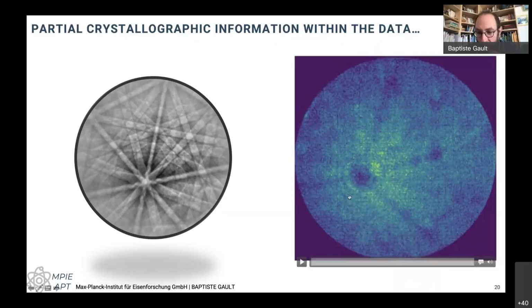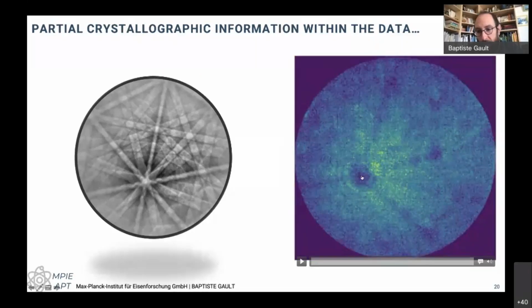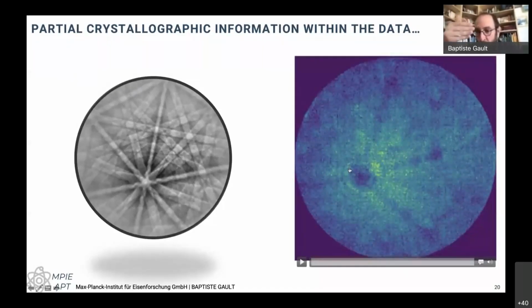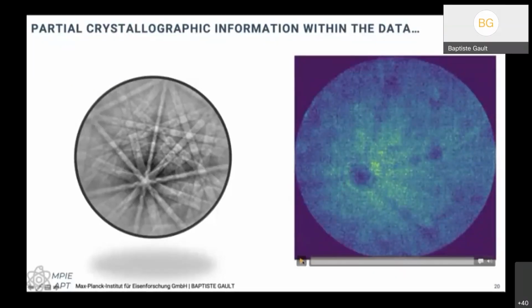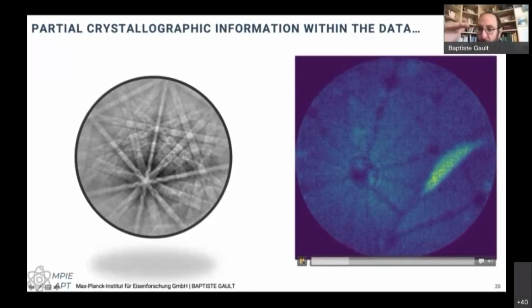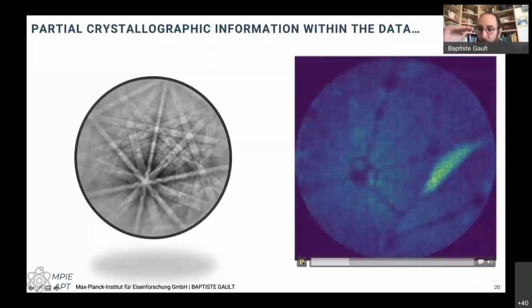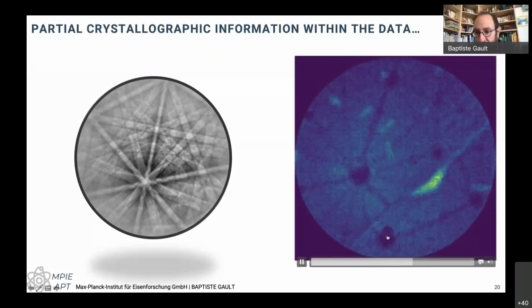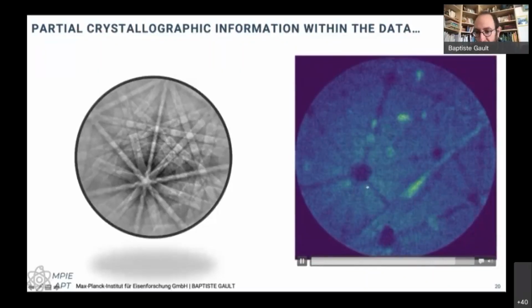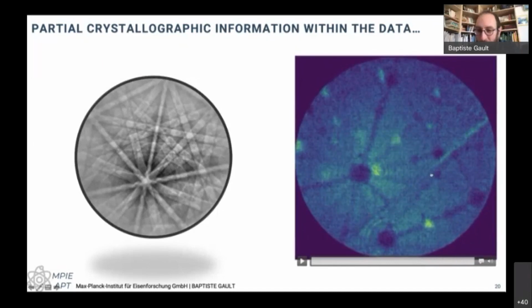But also, let me show you this. Here you see a certain pattern with a 3-fold symmetry, and then there's another 3-fold symmetry here. This is a 111 direction popping out of the specimen. And I'm just showing you one small histogram of these ion maps that are coming during an experiment. If I go down inside the specimen and look at the way the detector map evolves, I can see that it's changing. And here you can see actually this is the same set of planes, but across a grain boundary that is right there.